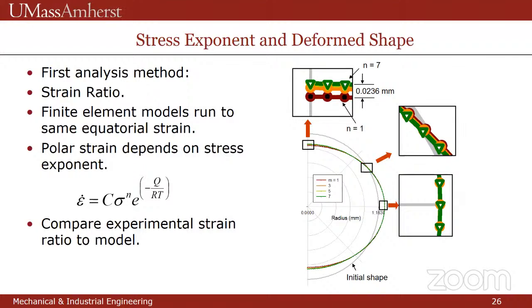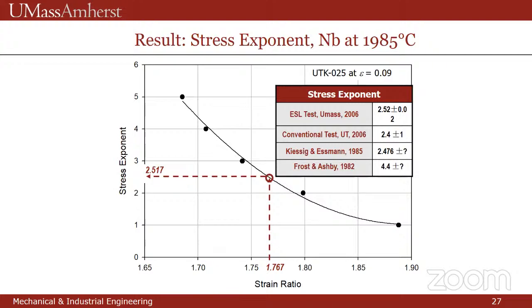We already had a precision metrology system in place that let us measure the small displacements of the sphere with an accuracy in the range of 100 parts per million. And so this displacement of 0.02 millimeters is very well within the capabilities of the system. Once we run the model, we just match up the experimental result here, 1.767, which corresponds to a stress exponent of 2.517. And yes, all 4 figures are significant. Or sorry, the first 3 are significant. So our test gives a stress exponent of 2.52 plus or minus 0.02. Our conventional test gave 2.4 plus or minus 1.